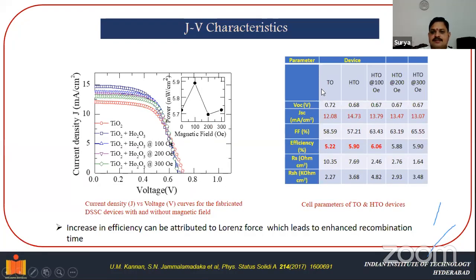This is the chart of the JV characteristics that we obtained before and after we applied the magnetic field. For instance, for titanium dioxide, the efficiency is 5.22 in the parent compound, and for the holmium oxide device, it is 5.90, and for holmium oxide with magnetic field, it is 6.06. We have repeated these experiments several times and could get the similar trend.